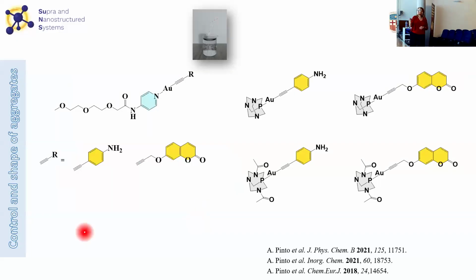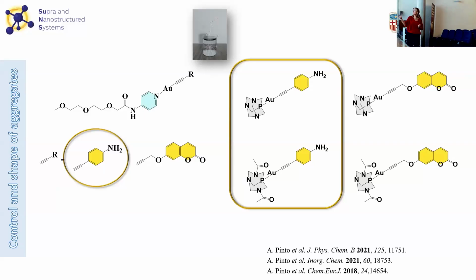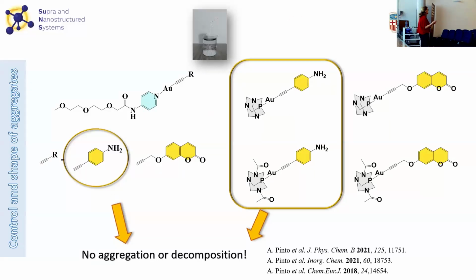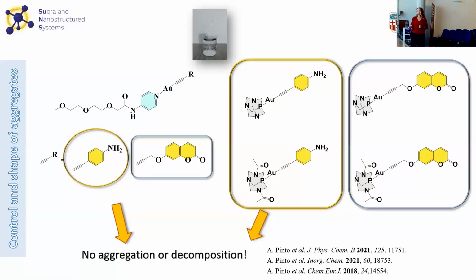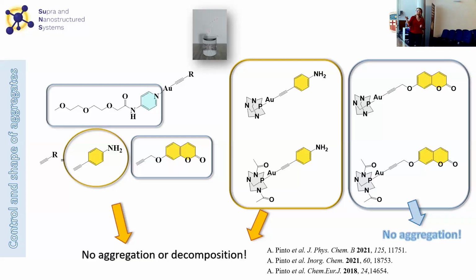So apart from the synthesis of this sample, what we wanted to see is the effect of the ligands on this self-assembly. So Andrea also synthesized some parent compounds having these water-soluble phosphanes instead of the pyridyl polyethylene glycol ligand. But what she observed is that with these compounds having ethinyl aniline, the compounds do not aggregate and even in some cases decompose. When we have the coumarin, also with the phosphanes, the molecules were stable, but they also do not aggregate. So the presence of this pyridyl polyethylene glycol is necessary for the resulting supramolecular assembly.